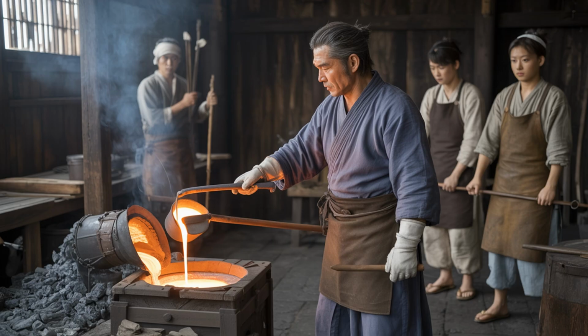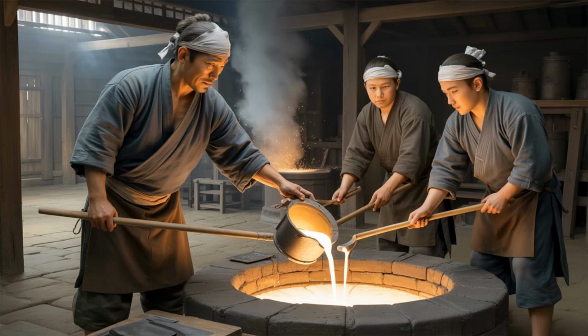The bronze smelter was usually a man who'd spent decades learning to read the color and behavior of molten metal like others read books. The copper went into the furnace first because it had a higher melting point than tin. Workers had to judge the exact moment when the copper reached the perfect temperature. Not just molten, but molten at exactly the right heat. Too cool, and it wouldn't mix properly with the tin. Too hot, and it would start to oxidize, creating impurities that would weaken the final bell. The experienced smelters could tell the temperature just by looking at the color and movement of the liquid metal. It was like having supernatural powers, except the superpowers were earned through years of burns, mistakes, and hard-won knowledge.